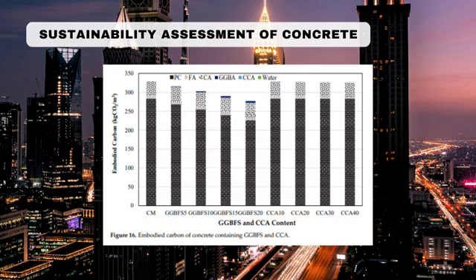Embodied carbon is recorded as 3.95%, 7.90%, 11.84%, and 15.76% while utilizing GGBFS levels of 5%, 10%, 15%, and 20% respectively, and 0.3%, 0.4%, 0.6%, and 0.8% with CCA levels of 10%, 20%, 30%, and 40% respectively, less than that of concrete prepared with PC only. Also, the sustainability assessment shows that when the usage of GGBFS as a PC replacement along with CCA as an FA replacement increases in concrete, the embodied carbon decreases.